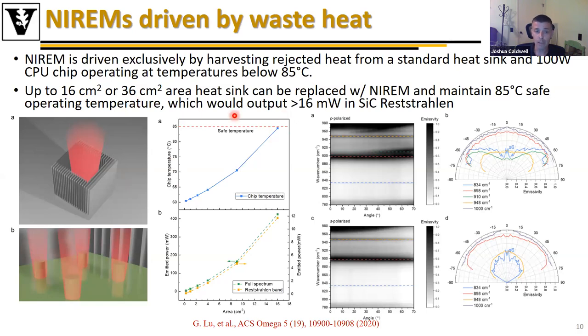Now, furthermore, if I look at the amount of light that I can get out from this device, look at the yellow curve here, this shouldn't be 16, this should be about 12 actually, sorry for that mistake there. But we get about 12 milliwatts within that Reststrahlen band from those localized resonances at only 85 degrees C. So this provides an opportunity to actually get a narrowband light source that could operate off of just waste heat from a local device without damaging that device in any way, and therefore could potentially provide some additional useful function.